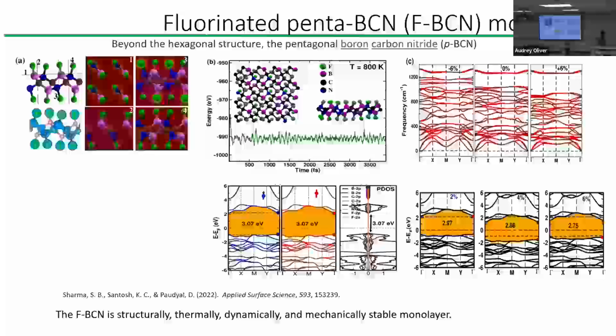And then we also look into mechanical properties, right? This is new 2D materials, right? We have this structure. We also look at thermal stability. This is using molecular dynamics. With temperature, still the structure is stable, right? And then we can calculate phonons with and without applying a strain, and it's still stable, right? We can look into electronic properties, clear band gap, right? With the strain, we can tune that band gap. So this structure is structurally, thermally, dynamically, and mechanically stable monolayer.